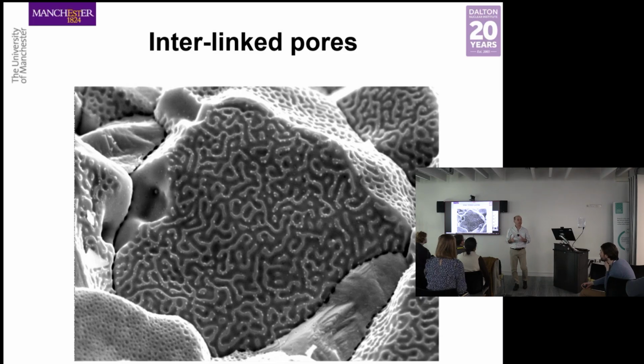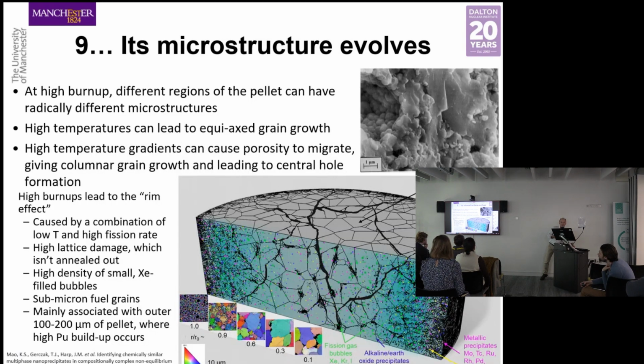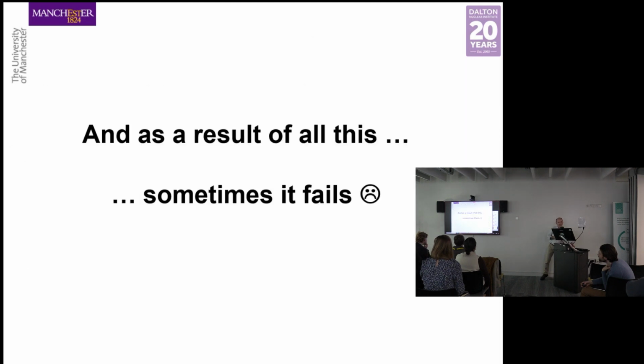The pressure inside the fuel rod therefore starts to go up. And the whole network of gas passages collapses because the thing that was keeping it open was the gas pressure inside. Once that gas pressure's gone, that network of bubbles tends to sinter again, and they will close, and the whole process begins again. So fission gas release is not a nice linear process. We get little bursts of gas being released. The gas bubble network collapses, and then a new gas bubble network starts to be created again. So we get these little bursts of gas actually being released from the fuel. And its microstructure evolves in really interesting ways that we don't have time to discuss, and as a result of all of that, sometimes the fuel fails, which is very sad.